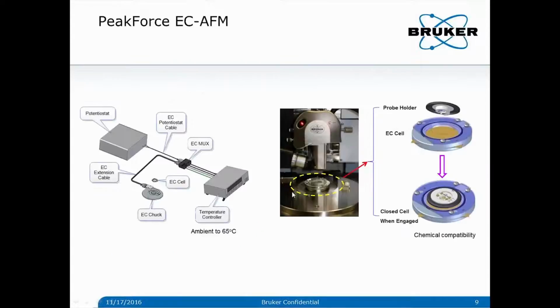And in this work, that Ravi is going to talk about, the primary technique we use is the peak force electrochemical AFM. So it is AFM again based on the peak force tapping. In this mode, the AFM performs peak force imaging on a working electrochemical system. For this system, there is also a built-in heater and a temperature control system, and this temperature control system allows ambient to 65 degrees C.